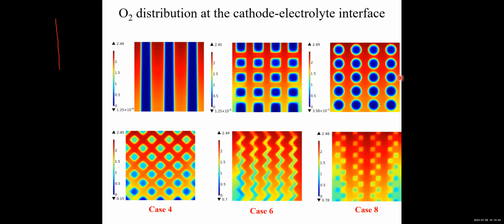Using different designs, for these two I think they are not very effective. But for the other designs, like case 4, 6, and 8, the oxygen concentration even under the rib can still be improved significantly, especially for these two figures, you don't see very low oxygen concentration, meaning the whole cell can perform very well. But for the other cases, when you see the dark blue color, the oxygen concentration is very low, meaning the local cell performance is very poor.